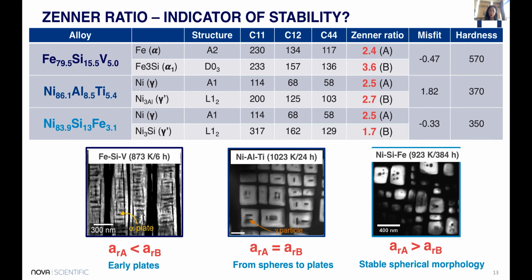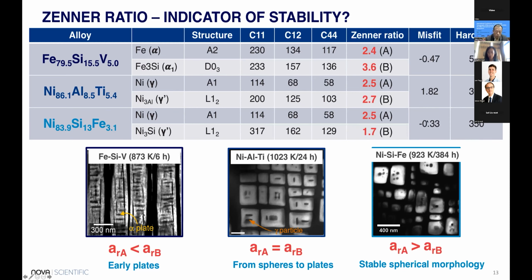We took a close look at a variety of such hierarchical alloys and their properties. Initially, we thought that the lattice misfit might be a direct indicator of how hierarchical particles would behave. However, the iron silicon vanadium alloy and the nickel silicon iron alloy have almost the same negative lattice misfit, but the evolution of hierarchical particles could not be more different. Of course, the iron silicon vanadium alloy has a BCC structure and the nickel silicon iron alloy an FCC structure, which needs to be considered too.